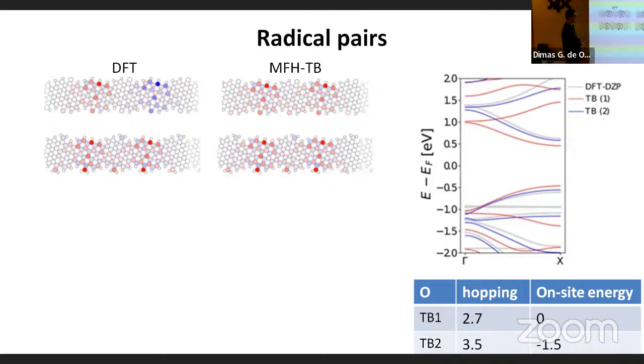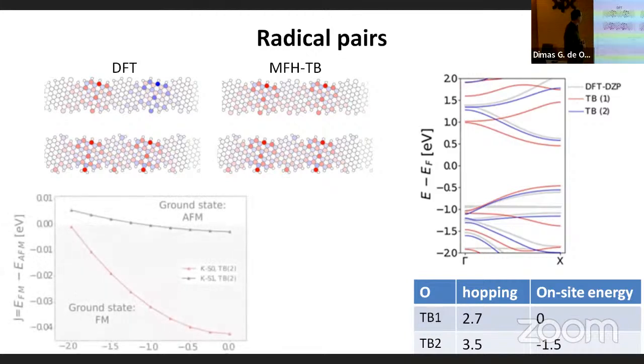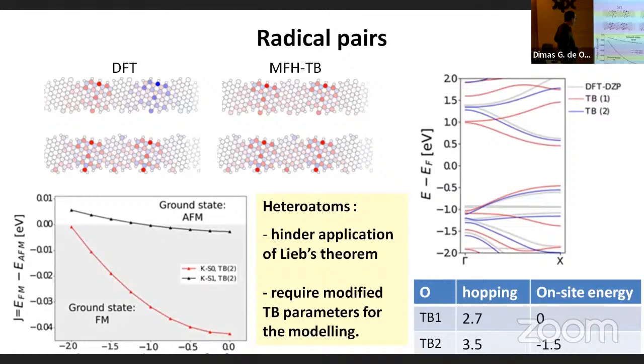And we do that by simply increasing the hopping amplitude across this oxygen-carbon bond. This is kind of intuitive because that bond length is much shorter, and then you would expect a larger hopping amplitude. And you also put some on-site energy because the oxygen atoms are more electronegative, and this makes it more favorable for the electrons to sit at those particular positions. And then basically by changing this, as you see, you get a much better fit now with the blue to the gray curves.